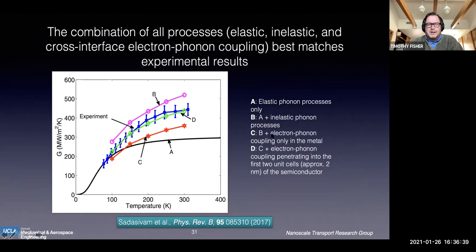C does this, those two with only electron phonon coupling. This is that sort of wave function interaction in the metal. And then D, which is the green one, the one that we care about, has electron phonon coupling through the first two unit cells, which is again enough. We judged it to be enough. And so this green curve fits the blue experimental data without any significant fitting factors.